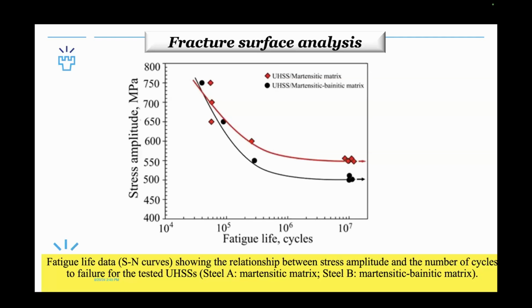Of course, we should focus on this one because our colleague Matias is familiar with it. He normally tests this fatigue limit point about 3, 4, 5 times to be sure. Here there is no fracture, so the fatigue limit is without failure at this stress amplitude. Of course, with increasing stress amplitude, fatigue life will decrease. But anyway, we can see that steel A, with fully martensite structure, shows higher fatigue life than steel B, including martensite and bainite 50%.